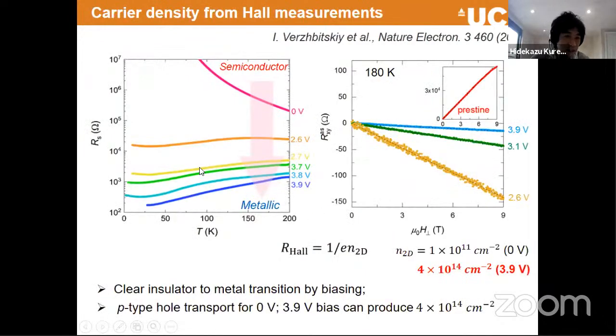Right, so then this is the resistance as a function of temperature. And as you can see, this is a quick check. When we don't dope, the temperature dependence looks like a semiconductor. But when we dope, you can see the temperature dependence becomes metallic. That's great news because then we are not only changing the resistance, but we can also see that the transport is more continuous.